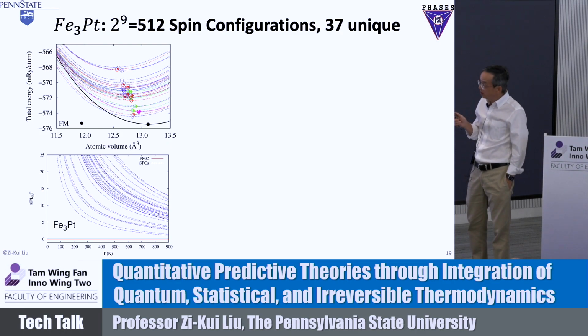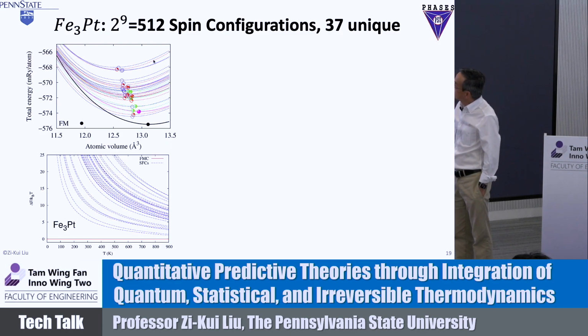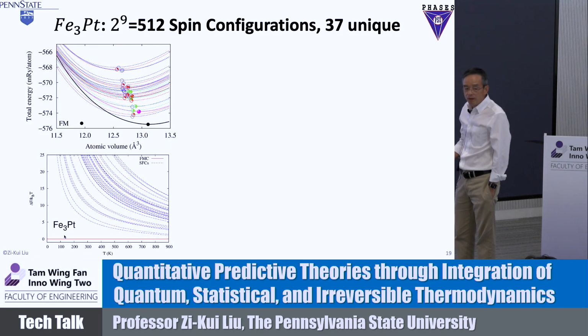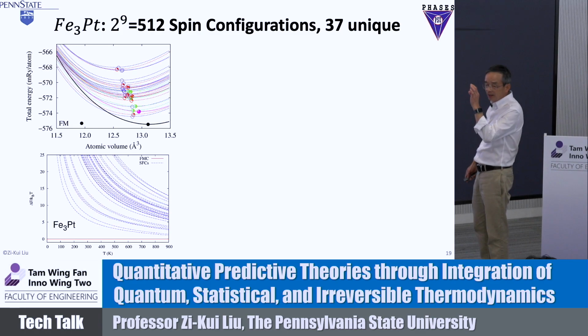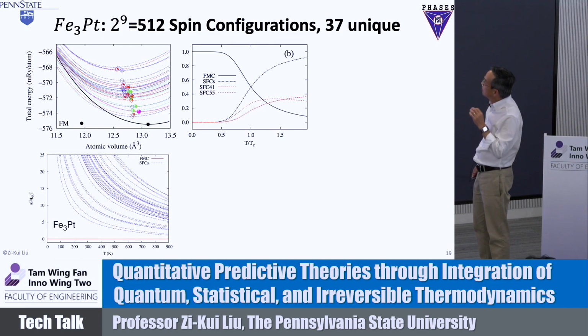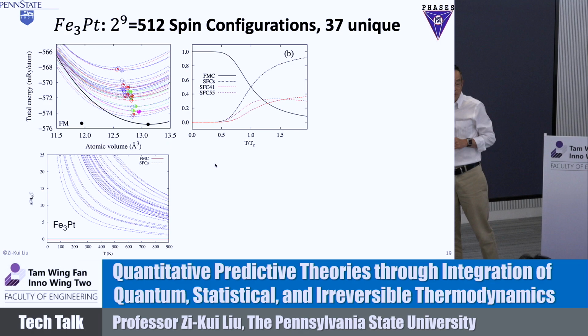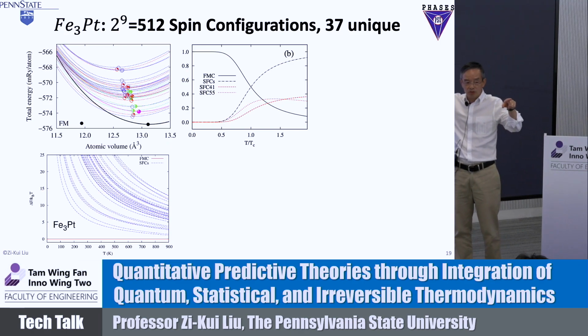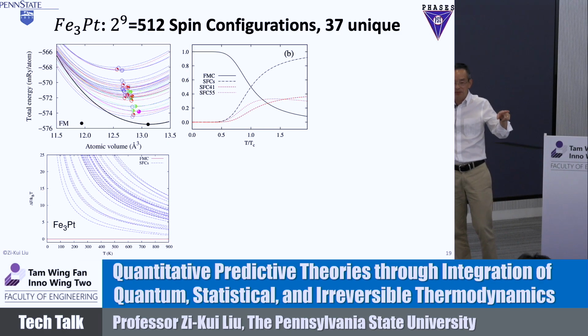The configurational energy. So it's very interesting that if you calculate the energy of the configuration, the ground state is always stable. If you look at the energy, you have no transition, because the ground state is always stable. You talk energy. However, it's a competition of probability, right? You see the probability at 0 Kelvin, the ground state is 100%. The non-ground state is 0. But when the temperature goes up, even though the ground state is still more stable, the population of the ground state starts to decrease. It can actually even decrease 15% at a high temperature, just because it's 1 against the 512. That's a number game, so you cannot compete. They're going to lose.